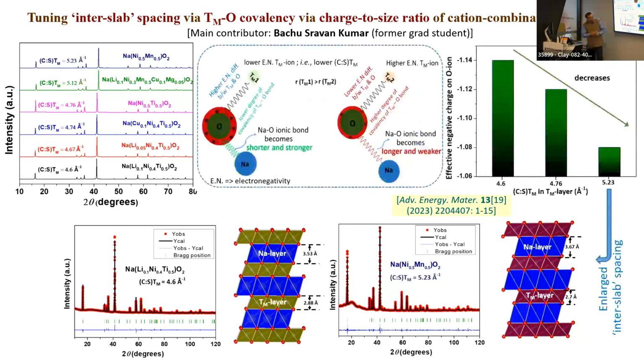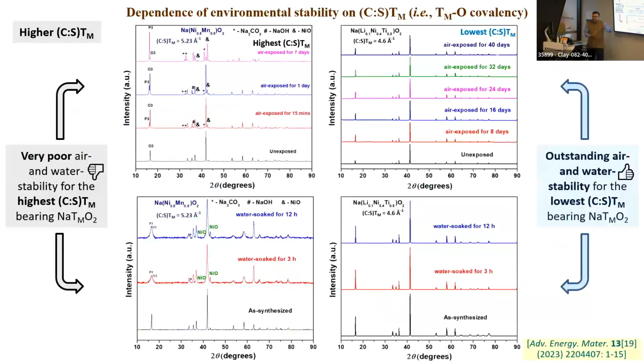Now, DFT calculations by my colleague Abhijit Chatterjee in IIT Bombay also show that it is in sync with what we thought. So when we have lower charge to size ratio, the effective negative charge on the oxygen ion is more negative, which means it will make my sodium oxygen bond stronger, as we had expected. Now let's move ahead. Let's see the results.